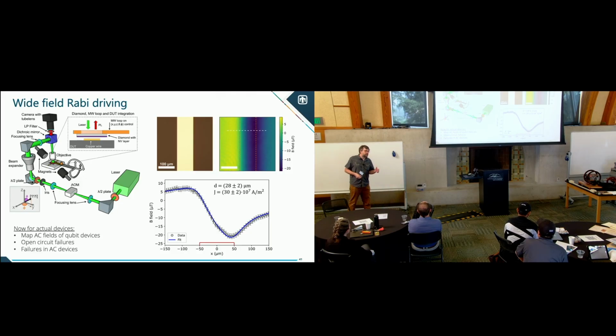So you can go from DC sensing, and then you can go from megahertz to gigahertz. That is the higher end of the range. I've got an example from the intermediate scale too. But nonetheless, we did this experiment, and we can show, in a wire, the AC magnetic field that gets mapped out, which perfectly matches what we expect.